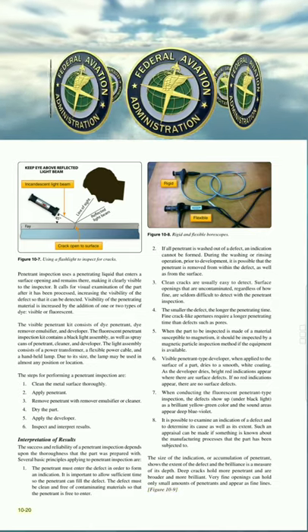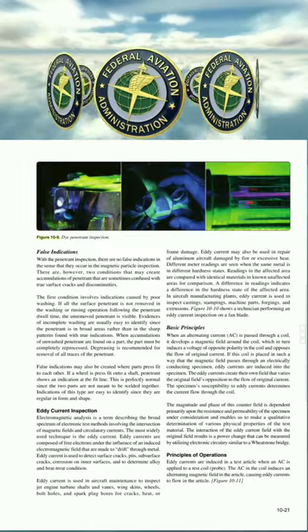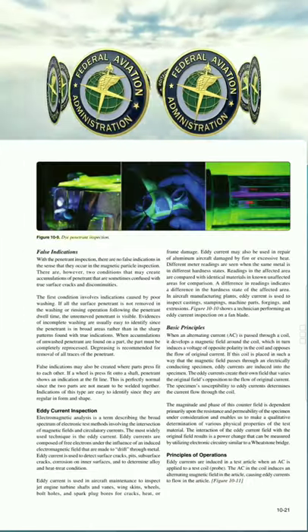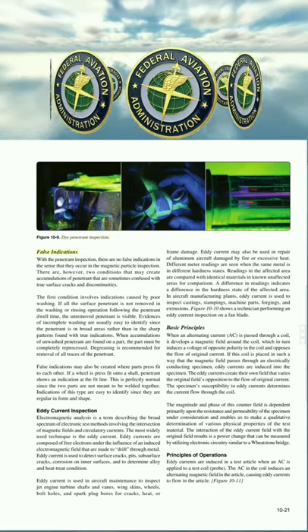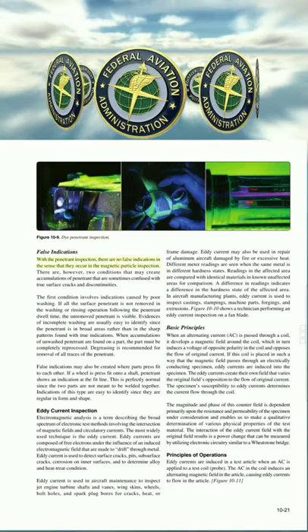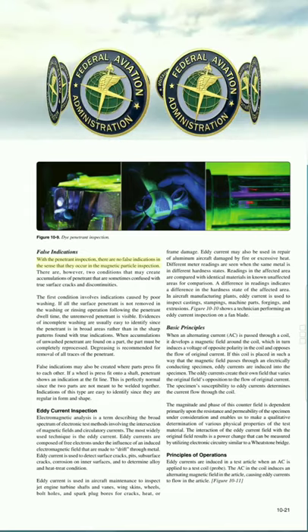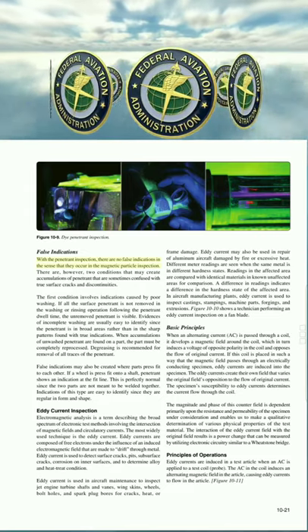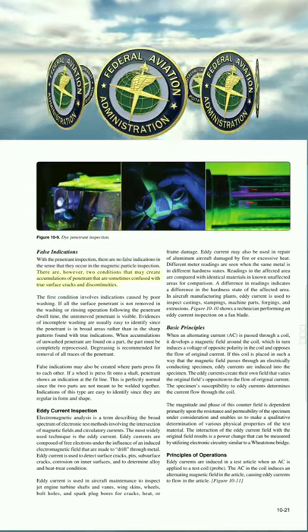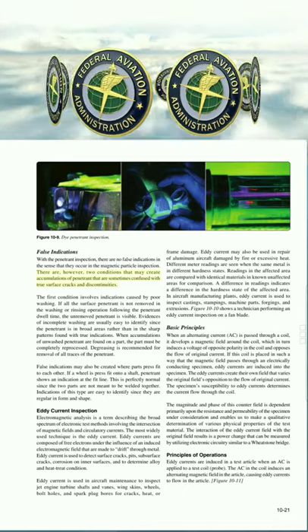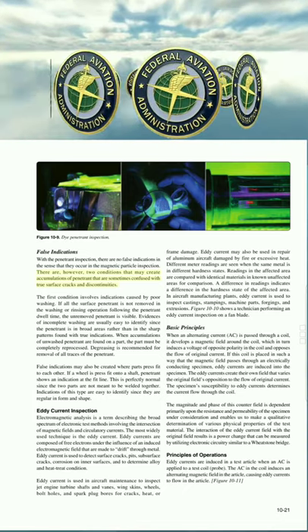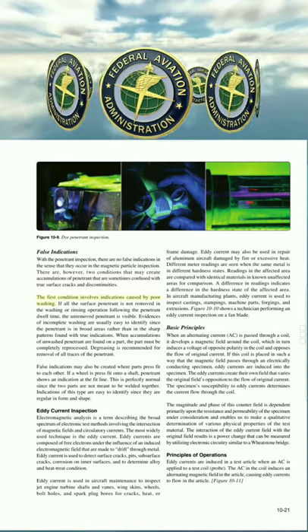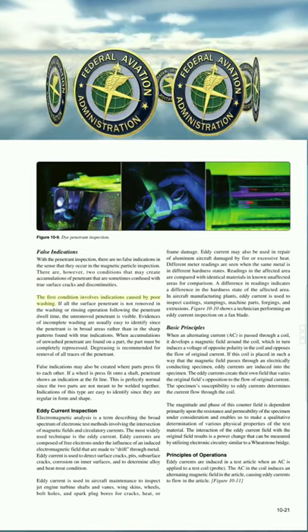Figure 10-9. Dye penetrant inspection. False indications. With the penetrant inspection, there are no false indications in the sense that they occur in the magnetic particle inspection. There are, however, two conditions that may create accumulations of penetrant that are sometimes confused with true surface cracks and discontinuities. The first condition involves indications caused by poor washing.